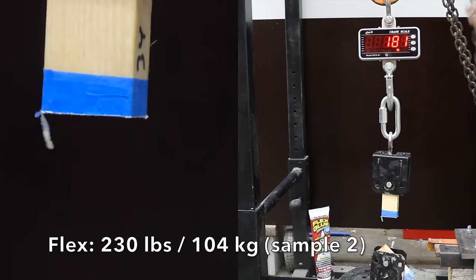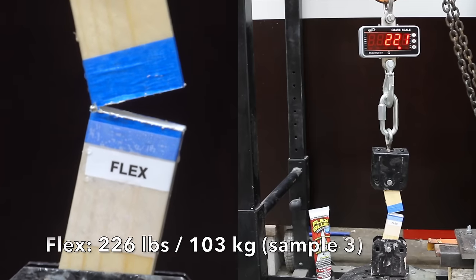Will water exposure hurt Flex? The first was only 152. The second was up a little to 230. The third was down a little to 226. So water exposure has had an impact on Flex as well.